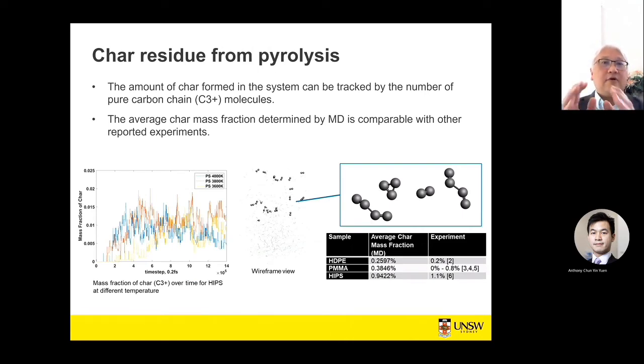One of the good things that comes out from this work is that we can look even at the charring behavior of this material. So for example, by tracking at least the carbon 3+ molecules, we can look at the percentage of char mass fraction of these three materials. For example, high-density polyethylene has a char fraction of roughly 0.3%, which is comparable with experiment, as well as PMMA and also high-impact polystyrene, which is close to 1%. So again, the richness of the data we obtained from molecular dynamics gives us a lot of insights into the polymer degradation behavior.